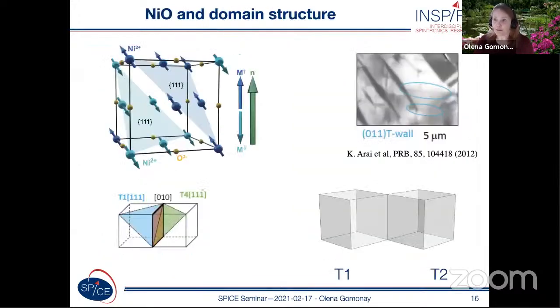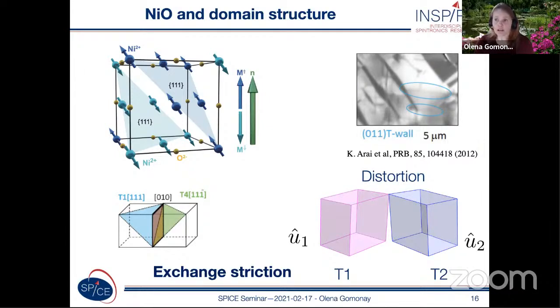More interesting and more peculiar effects appear in the antiferromagnets which have some special kind of domains, so-called T-domains. And a good example of such an antiferromagnet is given by nickel oxide and also cobalt oxide crystals. So in these materials, the magnetic ordering, the Néel vector, is parallel to a 111 crystallographic plane. And as we have 4 types of 111 planes, we have 4 types of T-domains. Interestingly, these T-domains have different not only magnetic order, but also different distortions. And these distortions are very large because they are induced by strong exchange striction.